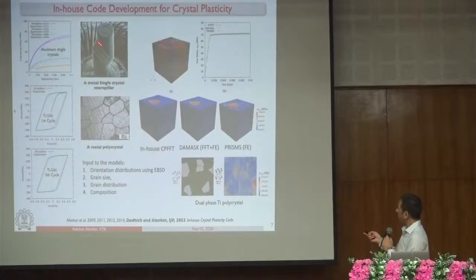Or fatigue. Our models can capture the behavior of single crystals, like you see in this chart. This is aluminum single crystal behavior for various crystallographic orientations. That means the loading axis is along a certain crystallographic axis, right? We can also simulate things like fatigue. This is an example of a titanium-5 aluminum single crystal. This particular alloy does not have vanadium. If you add vanadium, it will become the very well-known Ti-6 aluminum-4 vanadium alloy, which is used for aerospace and biomedical applications, right? This large amount of aluminum also restricts twinning. Otherwise, there is also a lot of twinning in titanium, right?